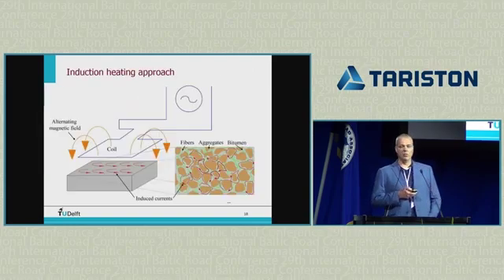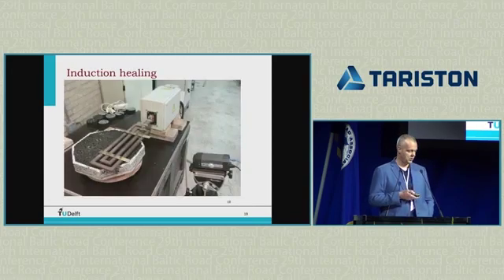As I said, then we come with an induction coil, you hold above your sample, that creates a magnetic field, then small eddy currents are going to flow through these fibers, then the fibers will heat up. Due to that eddy current, it will heat up the bitumen and close the cracks. So this is a test system that we use in the lab. So a small induction coil that we have there to test our samples, and then we check with infrared cameras what is happening to see how much the temperature increases.